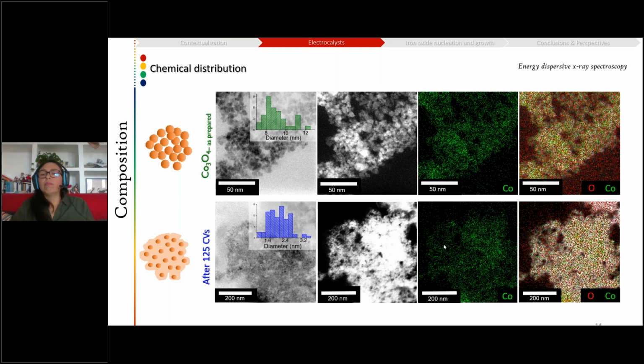And when we do the EDX, we are able to see that this amorphous layer is still composed of cobalt and oxygen, meaning that our cobalt didn't go away, at least not completely, but mostly amorphized and some of the crystalline parts, of course, decrease in size because of the amorphization.